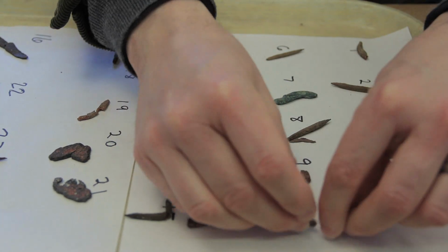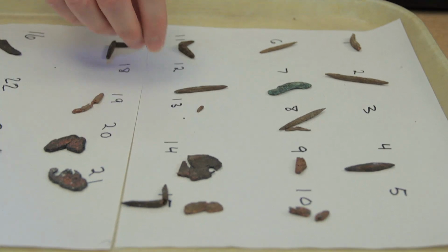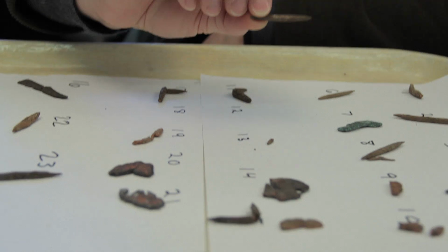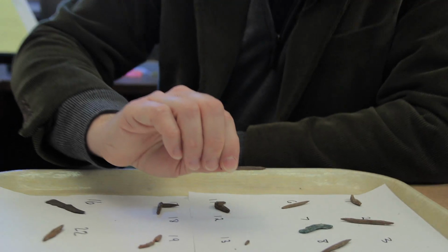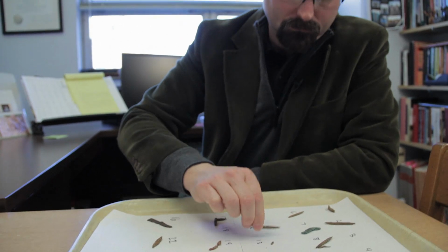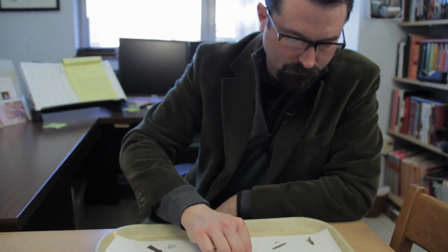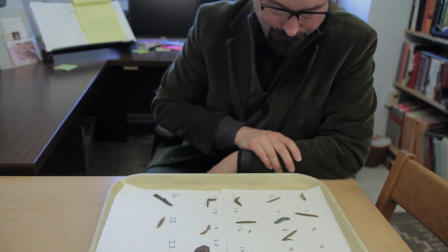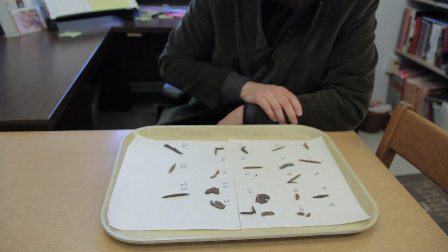However, our study and other studies have shown that it potentially is possible to make a useful tool by hammering native copper without annealing. In other words, if you can achieve the desired tool form before the tool gets brittle enough to actually fracture and break, then annealing isn't necessary. But annealing buys you a lot more working time to achieve the final desired form.